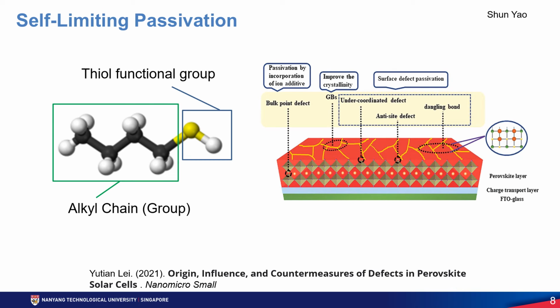In this part, I'm going to introduce the mechanism of self-limiting passivation. Since earlier solution and physical vapor deposition techniques face challenges to fully cover the silicon pyramids, due to the relatively high roughness of the perovskite film, the charge collection does not meet the expectations. So, the researchers applied SLP treatment on the perovskite film to enhance its properties. SLP has many advantages due to the presence of the alkyl group within the structure. The hydrophobicity is well enhanced. Therefore, the SLP treatment could improve the phase stability and device efficiency of the perovskite under different conditions.